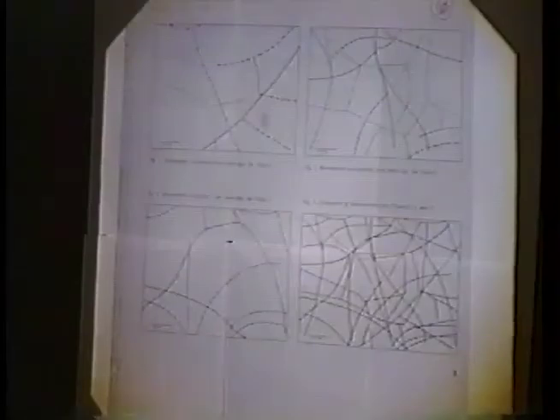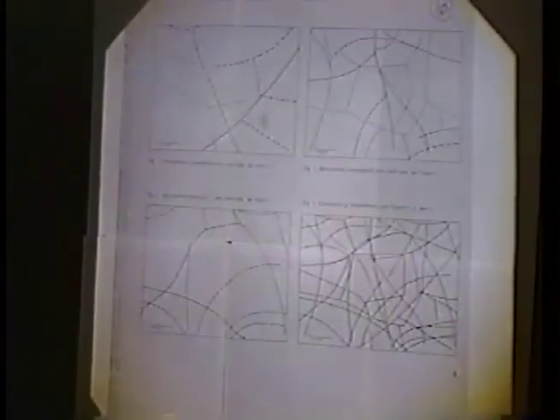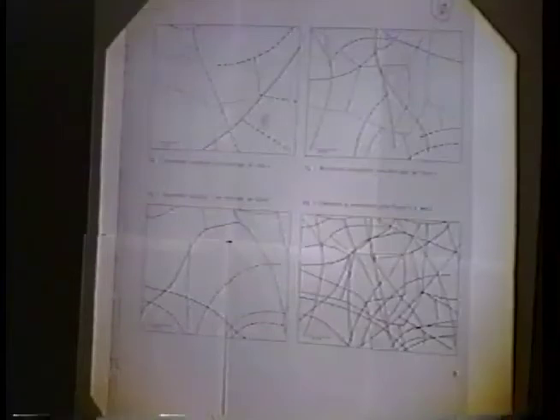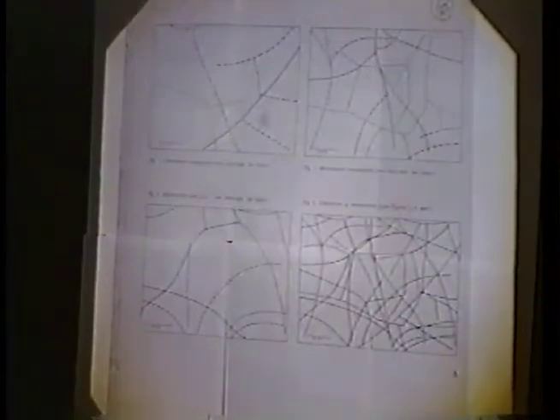But as the layer continues to develop, as it continues to build thickness on top of that first point where it's stress relieved, it builds another layer and then stress relieves that. So you get multiple layers of stress relieved chrome throughout the total thickness of the coating. And as I say, you can't see these until the liner's been stress relieved again, maybe in the operation of the engine. And then what you end up with is what I'm sure most of you have seen, and that's a chicken wire pattern on the chrome surface.